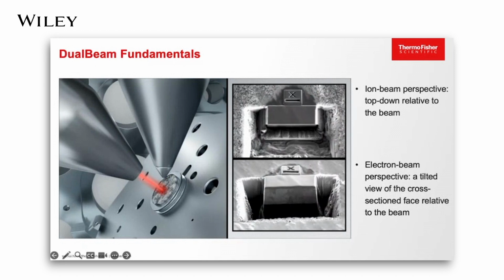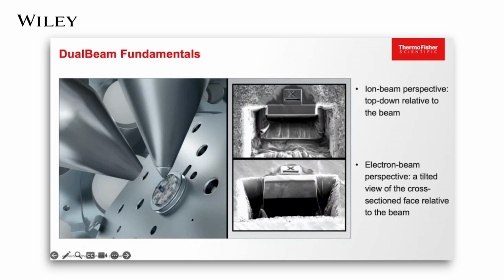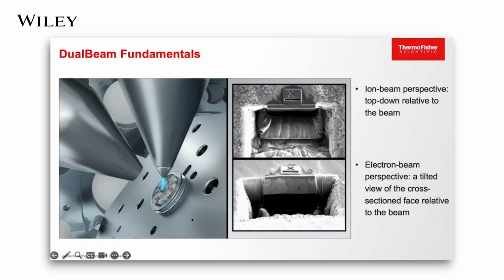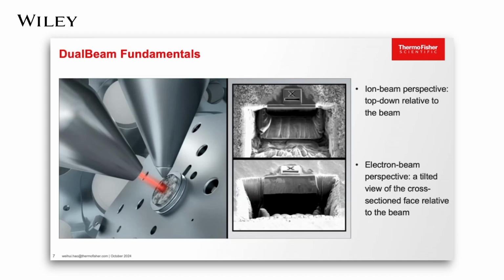Here, we introduce our dual beam technique. If we go into the microscope, we can observe the sample with SEM. Then the red beam we can see is actually cutting away and sputtering away materials with focused ion beam. In this particular example, we are able to take all these images and make a 3D rendering or do 3D reconstruction of that sample. But if we just want to expose one section of the sample site specifically, a dual beam does that quite well. This